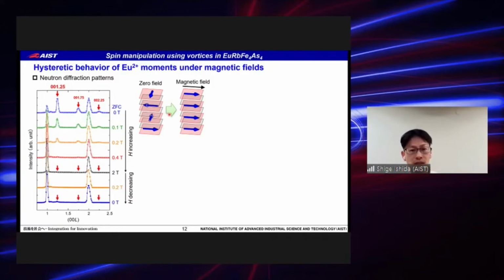This is what we expected from magnetization measurement. On the other hand, when we decrease the magnetic field to zero, we found that the intensity of the 00L plus minus 0.25 peaks does not recover. This means the ferromagnetic alignment is maintained although the external field is zero, demonstrating hysteretic behavior of the europium moment.